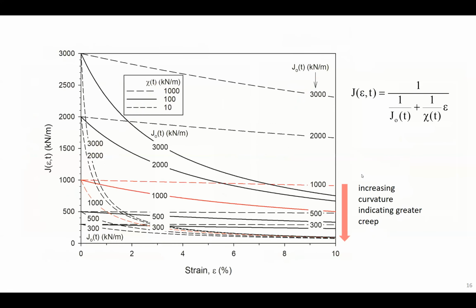And this slide shows some trends. Here we have plotted the compliance curves, and if you focus for a minute, because it's a busy slide, on the red curves, these are curves that have the same J naught term value, but they have decreasing values of this chi term, which means they're creepier. So as this chi term decreases, you can see how the curve is becoming more pronounced, indicating a product which is more creep susceptible.